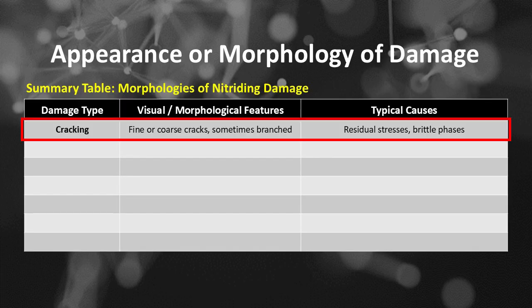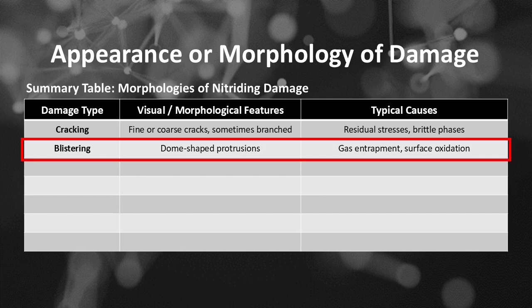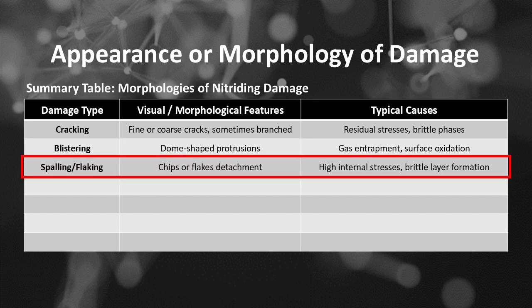Summary table of morphologies of nitriding damage. For damage type cracking, the visual or morphological features will be fine or coarse cracks, sometimes branched, and the typical causes will be residual stresses and brittle phases. For damage type blistering, the features will be dome-shaped protrusions, and the typical causes will be gas entrapment and surface oxidation.